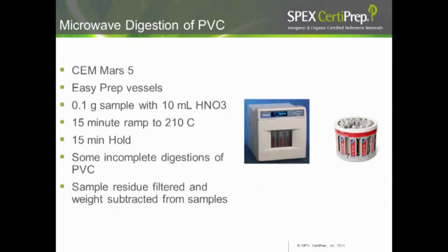Our first experiment was a digestion experiment. We used our CEM MARS 5 microwave with Easy Prep vessels. 0.1 grams of sample with 10 mL of nitric acid, and a pretty standard ramped temperature to 210 degrees Celsius with a 15-minute hold. What we did find is that some of our PVC samples, not all of them, did not digest completely, despite having tried to digest them several times.